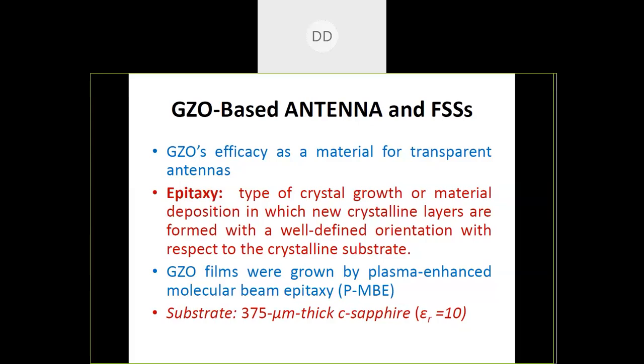In the development of the antennas which we are going to discuss, this epitaxy type of procedure was used for developing the films. More exactly, the plasma enhanced molecular beam epitaxy technique has been proposed by researchers. This work I have taken from one of the references. They used this particular approach for developing the antenna, and they used one particular substrate named c-sapphire substrate with epsilon r equal to 10, and the thickness of the substrate is 375 micrometer.